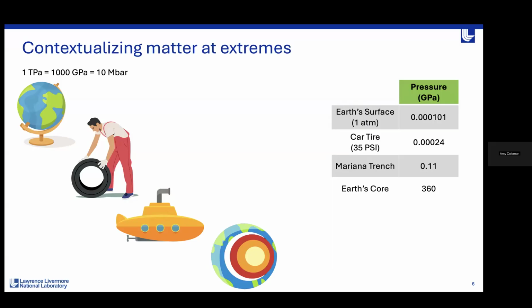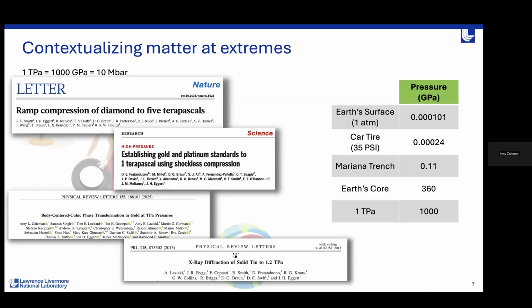Now, this isn't the full extent of what we can reach. If we use very intense laser drives and very cleverly designed experiments, we can actually extend our reach up into the terapascal regime, so pressures in excess of 1,000 gigapascal. And what I'm showing on the left-hand side here are a series of papers which showcase beautiful data sets collected at the National Ignition Facility here at Livermore, where all of these materials have been taken to the most extreme pressures that we can practically make and study on Earth in the lab.